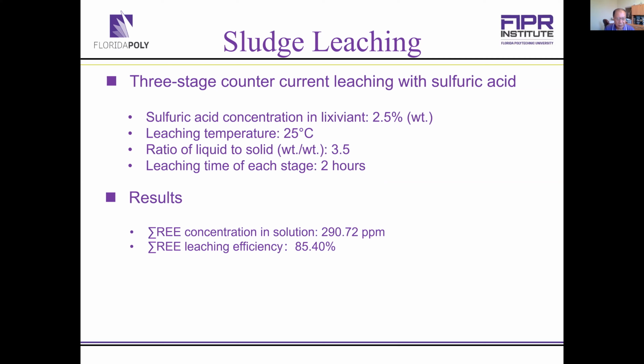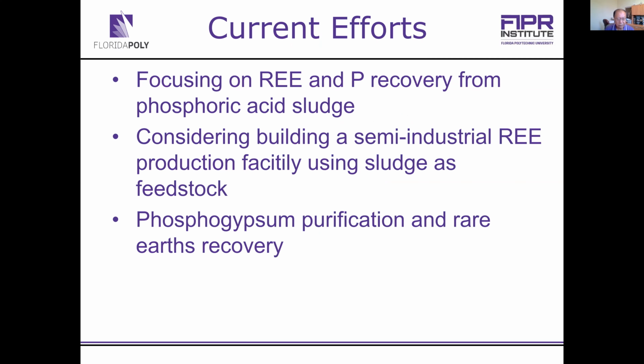For sludge leaching, three-stage counter current leaching with the sulfuric acid, the recovery is 85%, and rare earth concentration in the leachate is about 290 ppm. Currently, under the CMI program, we focus on recovery of phosphorus and rare earth from phosphoric acid sludge.